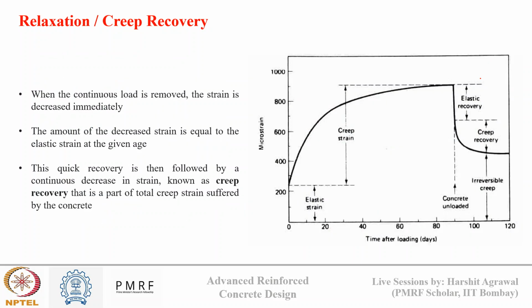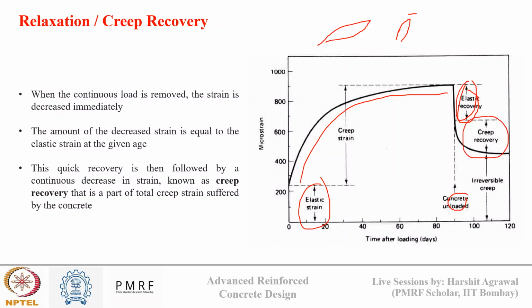And what happens when we remove the loading? There is a process known as relaxation, or creep recovery. You see here in the diagram, after elastic strain, there is creep strain until the unloading. Now the concrete is unloaded, so the elastic part will show some recovery, as we saw from the hysteresis. We talked about how, if we are not applying the load up to the ultimate load, there can be a slight recovery in the strain. So that is the hysteresis effect in the elastic recovery. Some part of the creep will also recover, based on the amount of cracking that has occurred. However, there will be a big irreversible creep part in the system due to the cracking that the concrete has suffered until this loading period. So this is a representation of creep recovery or creep relaxation.